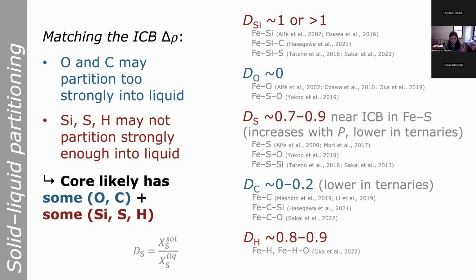So this suggests that the core probably has some oxygen and/or carbon in it, and also some silicon, sulfur, and/or hydrogen in it, to end up with a D somewhere in the middle that's going to be able to explain that density contrast. Although it's not trivial to convert from a density contrast to a composition, partly because it's a non-unique solution, but partly also we need to understand exactly how much each of these elements will affect the density at these conditions.